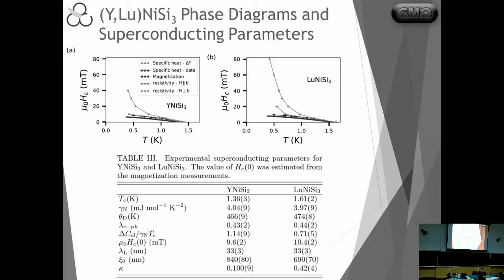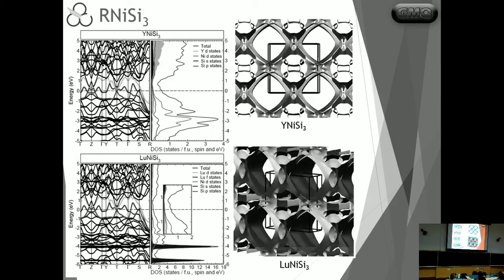Also, as part of this work, Daisy is working with Jorge in Colombia and did the electronic structure simulations for us. And from the electronic structure, we can see that there are 3 different bands that participate in the Fermi surface and therefore in the production of superconductivity here. 2 hole-like bands and 1 electron-like band like this, both for yttrium and lutetium. The Fermi surface, as you can see, is highly anisotropic with these cylindrical channels along the b-axis, which shows that there's really very little conductance along the b-axis like that.